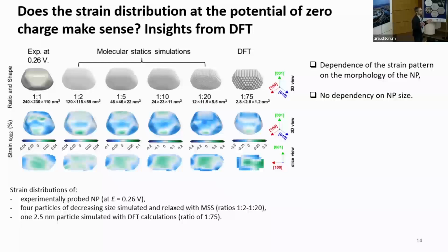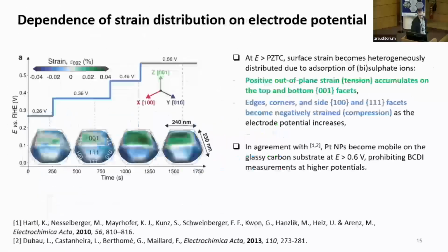What matters for the strain distribution is only the morphology of the platinum nanoparticle. So by changing the proportion of edges and corners, you will change the strain distribution. That explains a lot of what we are doing in electrocatalysis.